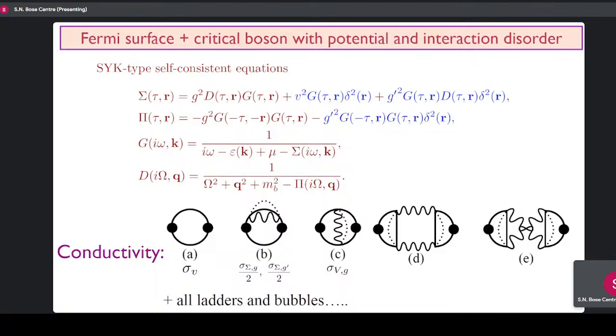This comes from the random potential. This is also sigma is G times D, but there's a delta function of r, telling us that this is due to local disorder. There's no disorder here at all. So the blue terms are very much like the Yukawa-SYK model, but there's a very subtle way in which space and frequencies are all mixed up. Anyway, you have to solve these equations and then compute transport.